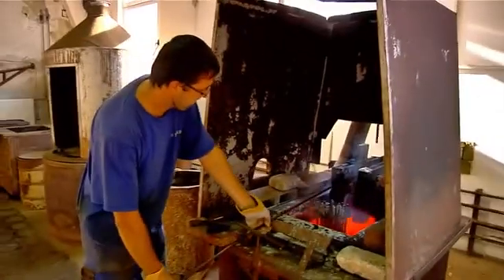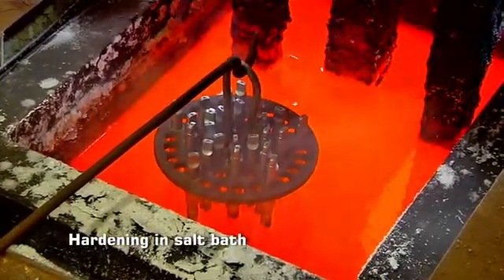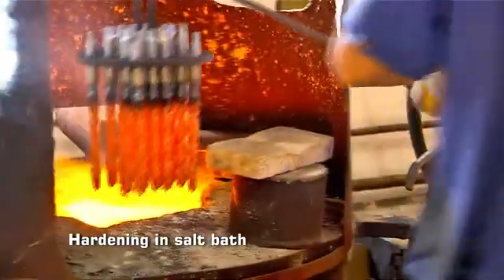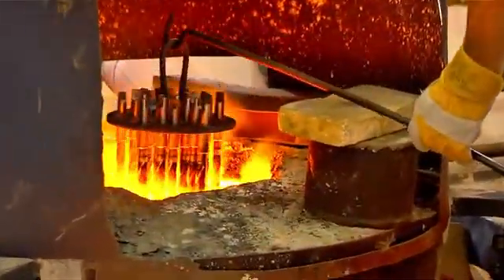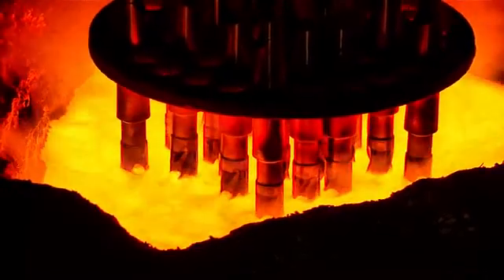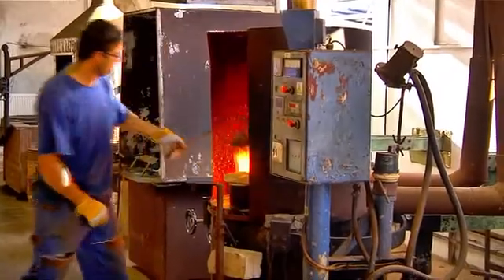The next operation is hardening. High-speed steel parts of drills are in two steps immersed into a 1260°C hot salt bath. High-speed steel acquires precious attributes like hardness and strength, and it is right here where it gets its significant attributes for cutting tools.